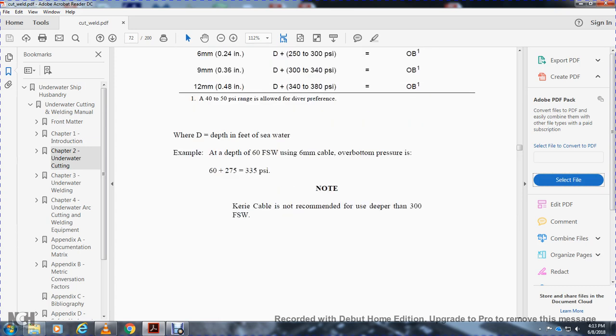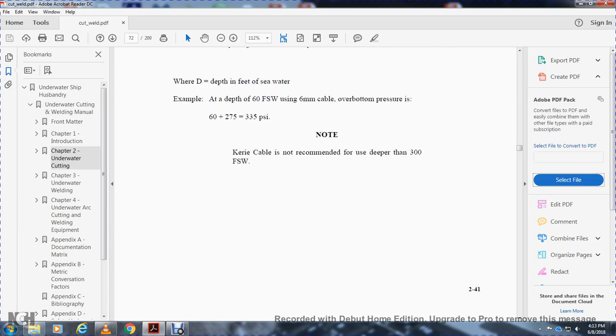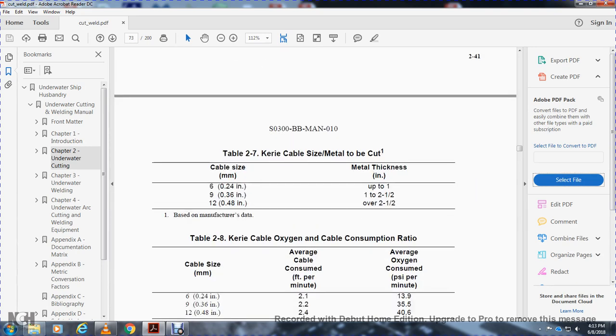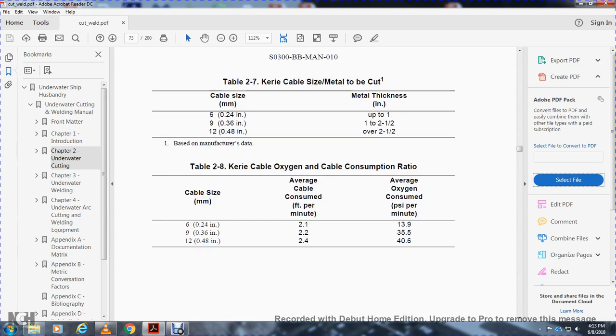Kerie Cable is not recommended for depths deeper than 300 feet of salt water. Cable size: 6mm for up to 1 inch of metal, 9mm for 1 to 2.5 inch metal thickness, and 12mm for over 2.5 inches of metal thickness.